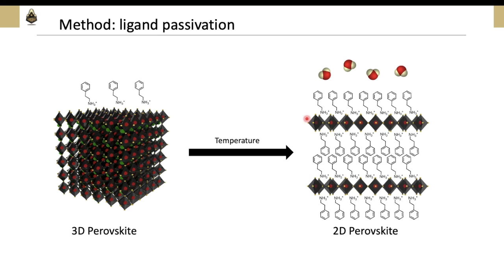2D perovskites are lower dimensional material with the same octahedral structure as 3D perovskites. The difference is that the charge carriers in 2D perovskites move in the horizontal direction, since organic tails create insulating spacing and inhibit charge transportation in the vertical direction.